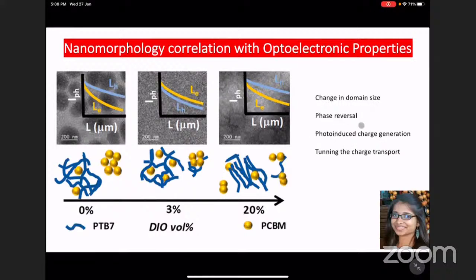We see a phase reversal. What was dark becomes white here. So you see the photo-induced charge generation efficiency gets changed. Here you have the fullerene aggregated. Here you have chain aggregation.